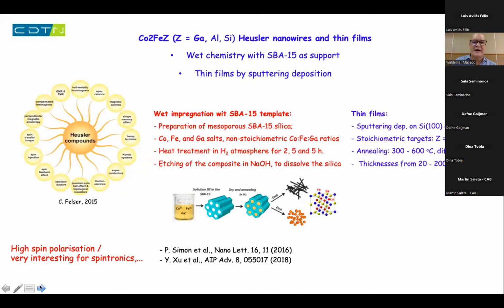Okay, and just to finish, what we are doing now is growing nanostructures of iron Heusler alloys based on cobalt-2 iron, and we are comparing nanowires grown by wet chemistry with thin films grown by sputtering, because with these materials it's not that easy. The magnetic properties of the Heusler alloys depend very much on the chemical order of the materials. I forgot to put a slide here, but it's not that easy to get the Heusler alloys in the nano regime. Okay, and we are doing it by using this silica template.